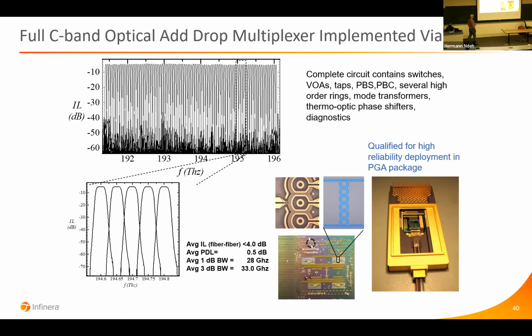In fact, this is what we did at Infinera. We purchased a company that had this technology called Little Optics. This was back in 2006, and then we further developed the technology at Infinera. You can see some of these micro ring resonators. These have heaters integrated upon them, and with this, we can make very sharp gigahertz bandwidth tunable filters. This is actually a commercialized device that we deployed at Infinera, an optical add drop multiplexer using this low loss glass. And because we could use the low loss glass, it had many dBs less loss than you would have if you made an equivalent.